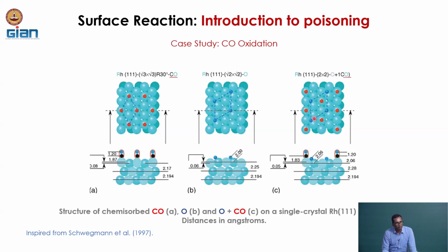So, what happens is that when the CO has a much stronger affinity to bind to the rhodium surface and a significant amount of the rhodium surface is covered with CO, then the oxygen adsorption is hindered and the reactivity goes down. Unless oxygen is adsorbed, the CO cannot react with the adsorbed oxygen, it cannot do the oxidation reaction, that is the CO2 formation.